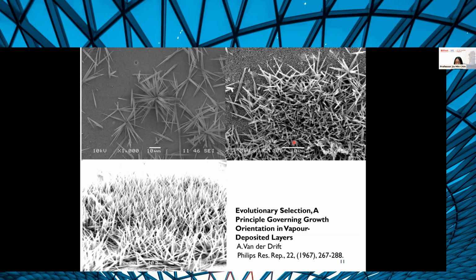Whereas towards the center, where you get slightly denser growth, you see that the needles are a little bit better oriented relative to the ones here. So they are a little bit more vertical. And when I first looked at this, I thought, what's going on here? And it turns out that this is a well-known phenomenon in crystal growth, which is called evolutionary selection, described by Van der Drift in 1967.